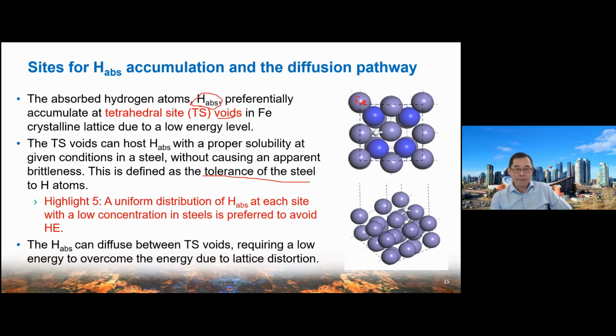At the same time, if the hydrogen is trapped or located at one TS site, it can also diffuse to another TS site. The diffusion between one TS and another TS does not need a significant driving force, because the hydrogen atom has a small size, and going from one TS to another usually causes only a little lattice distortion. That's why the energy barrier is not significant. So a hydrogen atom at a TS site can diffuse freely inside the steel. If this happens uniformly in the steel, we don't worry about hydrogen embrittlement.